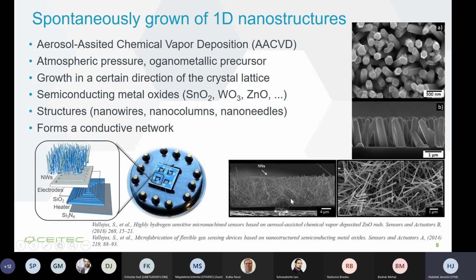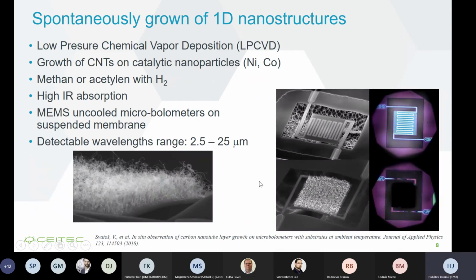The uncooled microbolometer is fabricated by MEMS technology, and we increased the sensitivity 4 times using this technique, and also the detectable wavelength range was increased up to 25 micrometers as a maximum. It is higher, but it is difficult to measure.